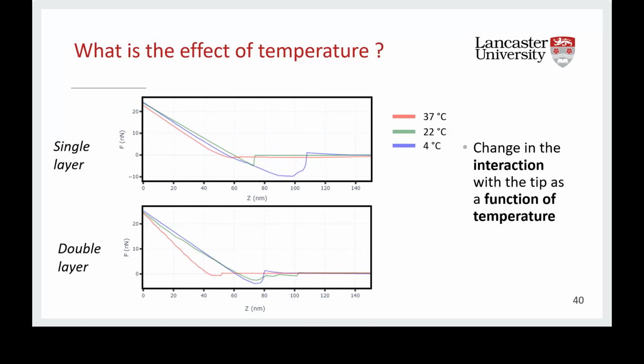If we start with the first curve at 37 degrees Celsius, we can see that the force is just 0 and then ramps up, meaning that actually there is no interaction between the tip and the coating. So at 37 degrees Celsius, the coating is hydrophobic. Then as the temperature drops to 22 and 4 degrees Celsius, you can see that a minimum of the force is appearing, meaning that actually the coating becomes hydrophilic and now is interacting with the tip.